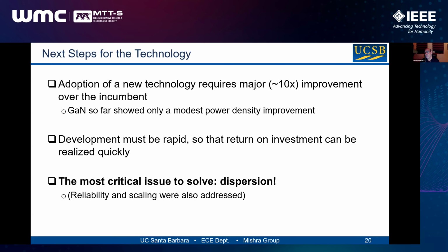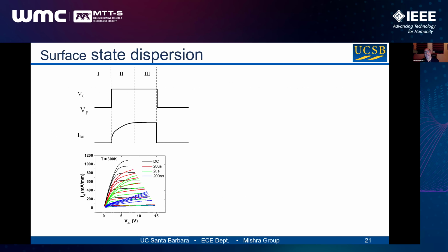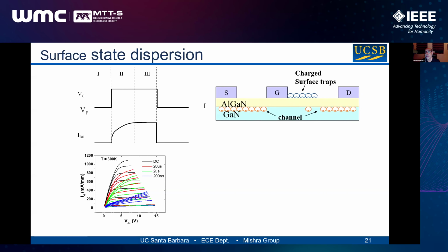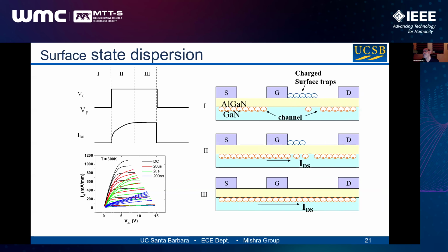But we had one big problem to solve, which was dispersion. So what happened is, if you made a DC device and you pulsed it, which we all have to do in microwave application, the current actually collapsed. At DC, it looked really good, an amp per millimeter. When we applied pulses to it, here's the blue, we had lost more than 50% of the current, and that's not good. And the reason for that always is traps.